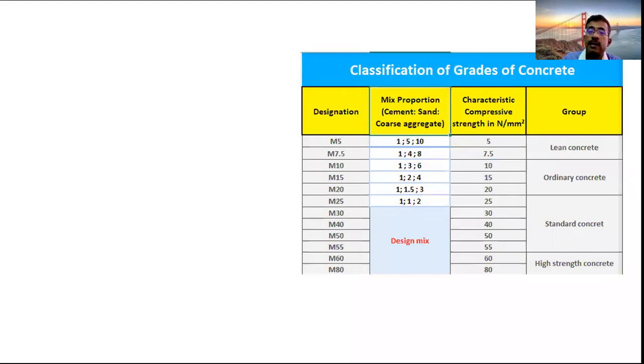So various grades are there, classification starting from M5 to M80 I've given. M30 onwards, we have to go for the design mix concrete. Up to M25, we can go for volume batching with the proportion. So starting from 1:5:10, M25 grade concrete comes with 1:1:2, M20 with 1:1.5:3. So volume batching is allowed up to M25. M30 grade and above, standard concrete with standard deviation, you have to design the concrete.